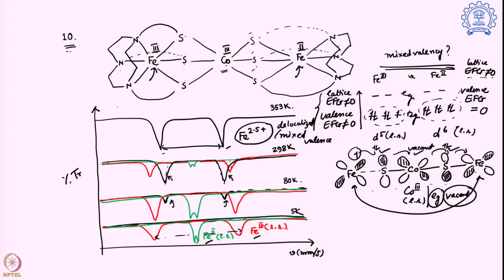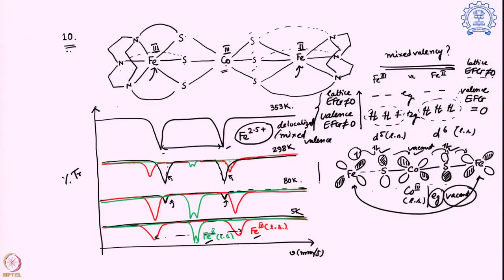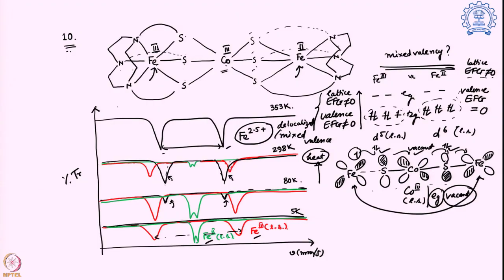So that can travel through that and reach the iron very easily, and that is what is actually happening. And over here the orientation of the cobalt, sulfur and iron is very important, so that there is a proper matching of the orbitals, and that is happening when we actually heat the system and enough dynamical flexibility is there so that they can achieve the orientation they want to have, and they can exchange electron very fast, and that is actually what is happening. And we are seeing this mixed valence system.